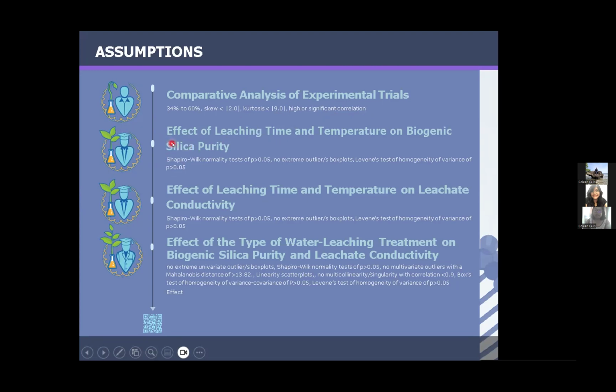Then the second portion of my results and discussion is the effect of leaching time and temperature on biogenic silica purity, and the effect of leaching time and temperature on leachate conductivity. Their assumptions are the same because both are two-way ANOVA. First is the Shapiro-Wilk normality test with p-values greater than 0.05, to know that the values are normal. Shapiro-Wilk is applicable when the number of data you are testing is less than 50.